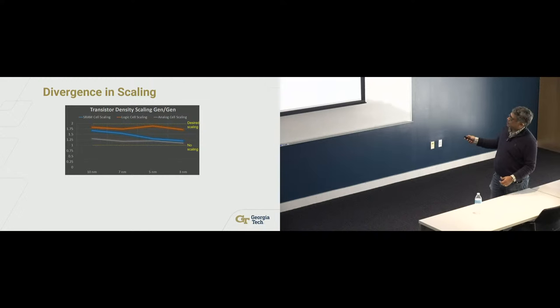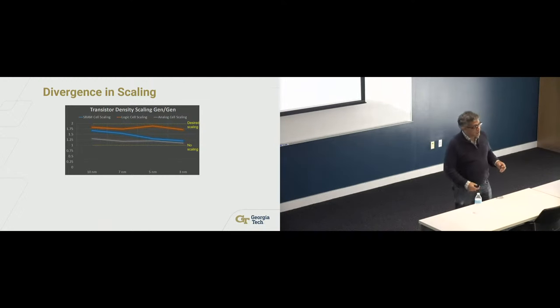If you look at the SRAM, which is also almost 50% of the chip, SRAM is the static random access memory, each cell containing 6 transistors. You can see that we used to do about 1.7 or so, and now it is almost approaching 1. If you hit 1, then there is no scaling. Then you're not actually shrinking the footprint of the SRAM cell. You can see that the SRAM scaling has slowed down. Part of the reason is that you need a perfectly matched pair in order to design an SRAM cell. It's a cross-coupled inverter. You have to have the perfect VTC characteristics for all your 100 billion cells that you're trying to do.